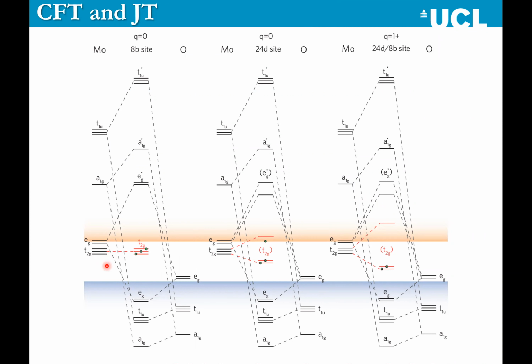So in your typical MoO6 octahedron, you have 3 T2g states, which would be non-bonding. This is for the 8B site, so the regular octahedron. And that's what we see in the band structure, 3 electrons trapped on these 3 non-bonding T2g states. When we go to the 24D site, it's actually akin to having a small Jahn-Teller distortion. So you end up with 2 states being pushed down in energy and 1 state pushed upwards in energy. And of course, because this pushes up above the bottom of the conduction band, the electron falls off it and ends up in the bottom of the conduction band. And this is for the neutral charge state.